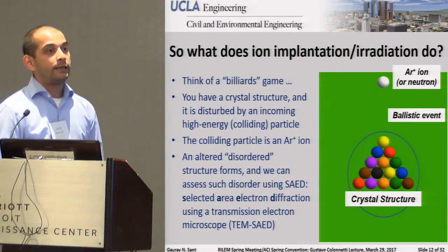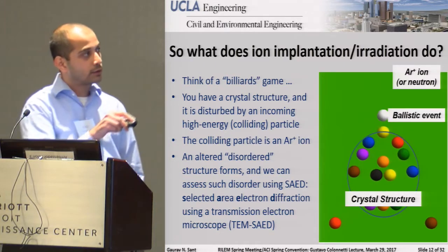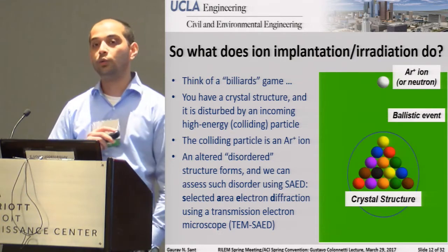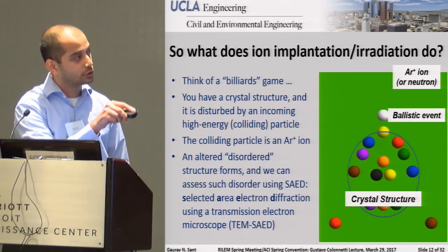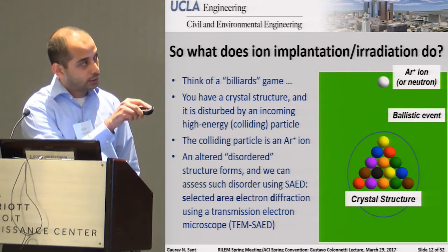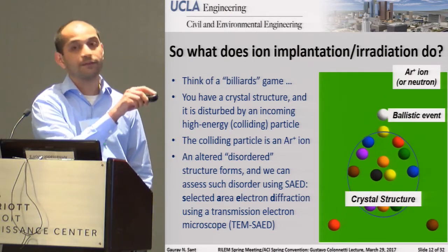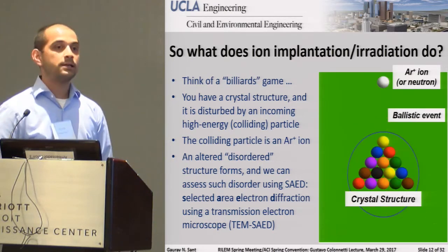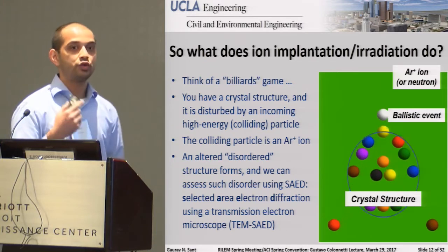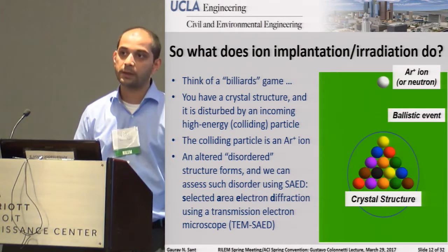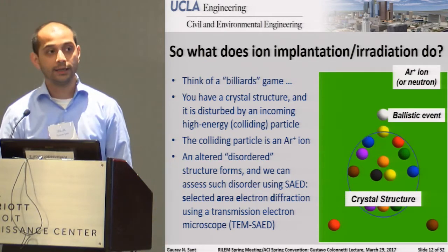But an important thing to point out, as you look at this cartoon over and over again, you will notice that going from the original structure, which looks like this, to this one, there's quite a significant increase in volume. And that's an important point to point out, because if you just take the first order view, you can start to explain why you get mechanical damage following irradiation.